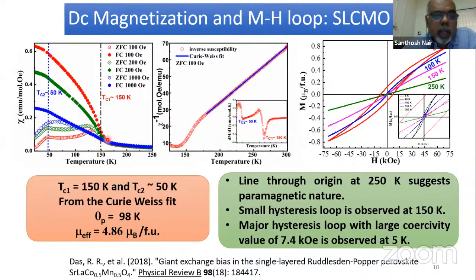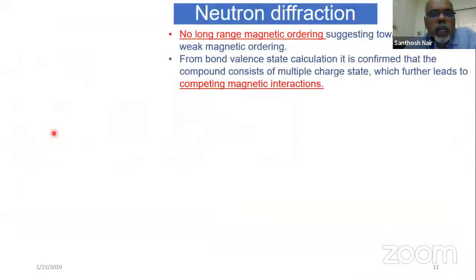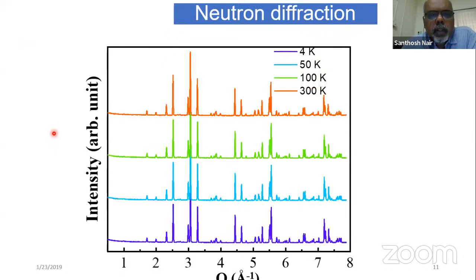One we call ferromagnetic, the other is something else. We don't know what it is. So how do we look at it? One way to do it, as you have seen Professor Yusuf talking about, is using neutron diffraction, which is a pretty common tool he uses, but we get to use it once in a while, in an important system, and we managed to do it. So what we find is, I just put the data at different temperatures to show that they're pretty identical. There are no extra peaks.